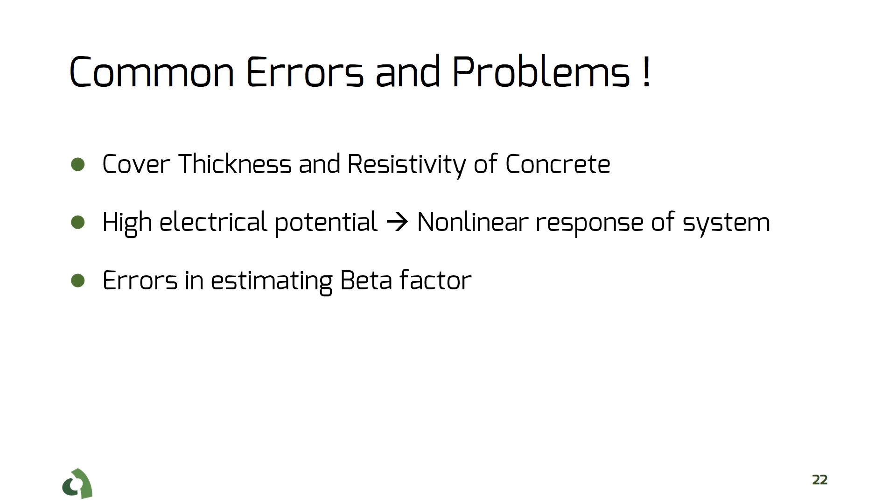Applying a higher polarization current will result in a potential drift of more than 25 millivolts, and the relationship between potential and current will move beyond the linear region.